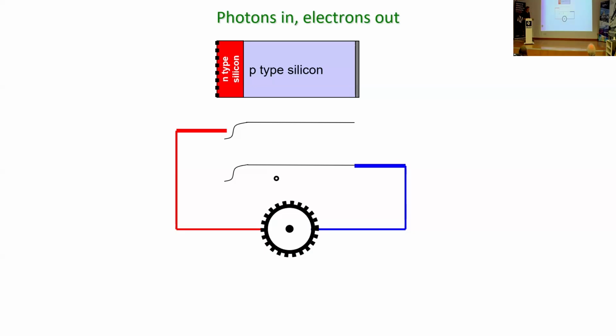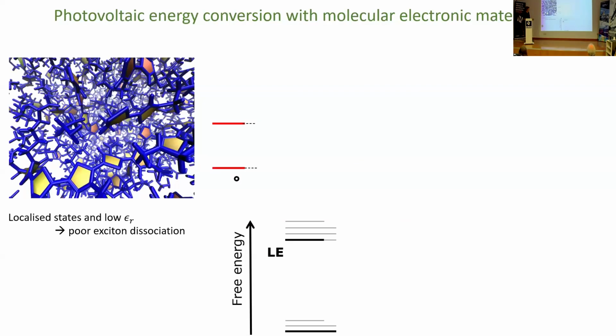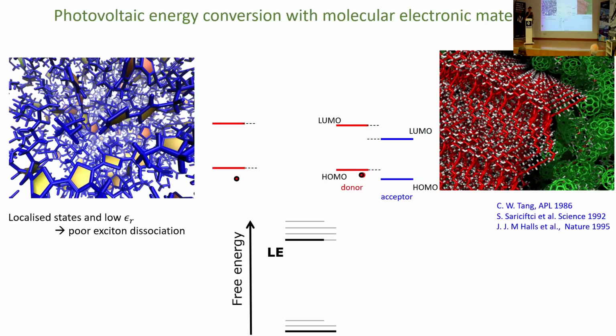Most often it's done with silicon. We're doing it with organic semiconductors, so molecular electronic materials, and there's various reasons to be interested in these, amongst them the basic scientific question. And when you try to do the first thing, which is to convert your photoexcited state into electron and hole in an organic semiconductor, that is problematic because the excited state is very tightly bound in that material and is more likely to decay back down to the ground state without separating. So if we want to actually drive a photocurrent, we have to get past that problem. And the way to do it is normally to use a combination of materials that creates an interface or a heterojunction where you have a driving force